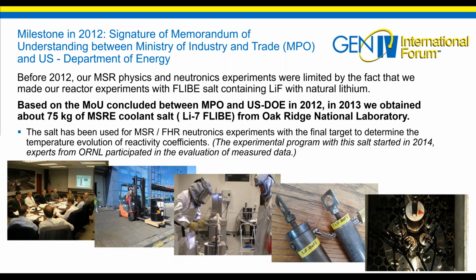So an important milestone was in 2012. Our experimental program in MSR physics and neutronics was limited by the fact that we did all experiments and neutronics measurements with FLiBe salt, which was composed of lithium fluoride with natural lithium. We had no lithium-7 fluoride, and our experiments were practically devalued by the presence of the lithium-6 isotope, which is in natural lithium.